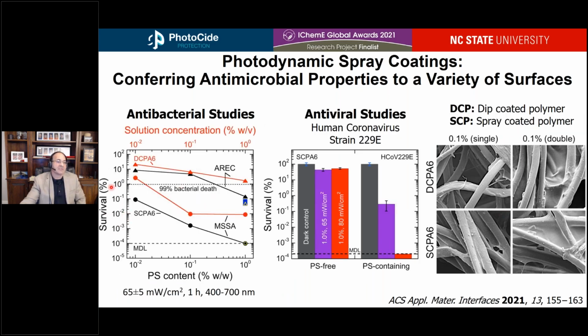I'll point out that the percent survival of the pathogens is noted here on a logarithmic scale. If we focus on the left-hand panel, MSSA is methicillin-susceptible Staphylococcus aureus. AREC is antibiotic-resistant E. coli. In both cases, we see photodynamic inactivation by our coating that's been sprayed onto these fibers, anywhere from 99.9% to essentially 100%, reaching our minimum detection limit. Again, illumination with just visible light.